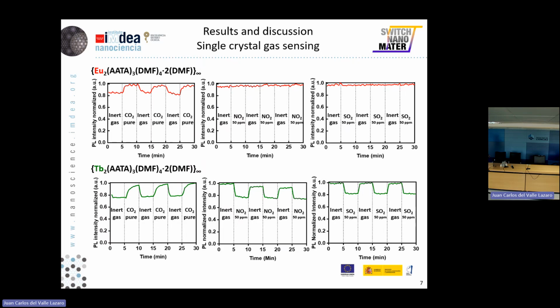These gases produce a decrease of about 20% in the maximum luminescence, so we thought about the possibility of developing a mixed material with europium and terbium emissions and using the europium as a blank for the measurements. But we tried the mixed crystalline synthesis without good results, because europium was the only metal that emits in this material.